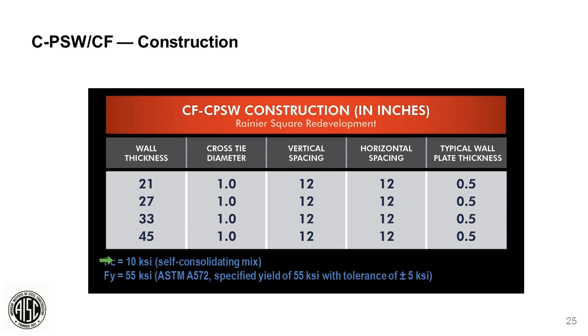We utilized a 10 KSI self-consolidating mix to fill it. The plates were ASTM A572. We specified a yield strength of 55 with a tolerance of 5 KSI each way because we wanted to have a good known predictability because we were doing a lot of capacity design principles. We wanted to have a very good tolerance in terms of where the yield range for the plate was. So that was a requirement for the project.